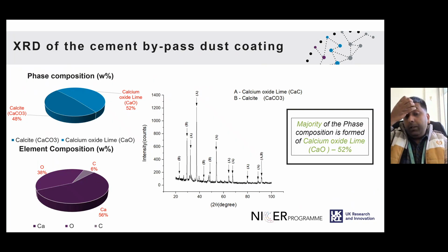So after we have performed the coating, what we found out from X-ray diffraction was the material has now become predominantly rich with calcium oxide rather than calcium carbonate. So this is one of the new learning and understanding on what has happened to the material before and after the spraying has been done. We aim to further gather the data on this particular front, but this is a very early stage result. And after we have done our complete analysis, we aim to publish this data for the open benefit of other users across the world.